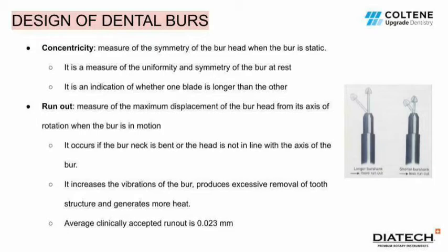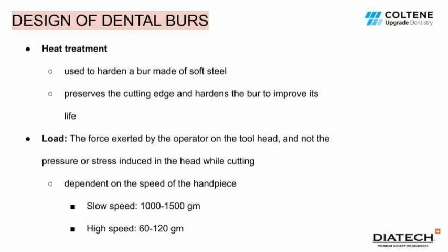It occurs if the burr neck is bent or the head is not in line with the axis of the burr. It increases the vibrations of the burr, produces excessive removal of tooth structure, and generates more heat. The average clinically accepted runout is 0.023 millimeters. Heat treatment is used to harden a burr made of soft steel. It preserves the cutting edge and hardens the burr to improve its life.